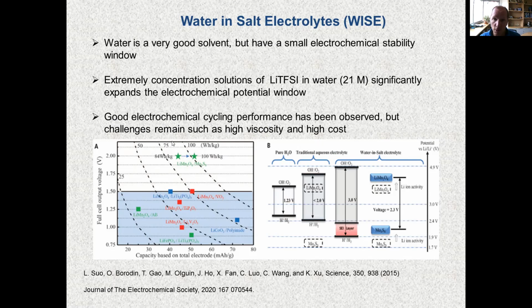And there are a lot of challenges that remain with these systems, especially related to high viscosity and also very high cost, because the lithium salts are typically the more expensive component of the electrolyte as opposed to the solvents. So if you go to very, very high concentrations of salt, you're going to see very large increases in the overall cost. However, these water-in-salt electrolytes are really very novel, very interesting, and very promising in terms of developing novel electrolyte formulations for the future.